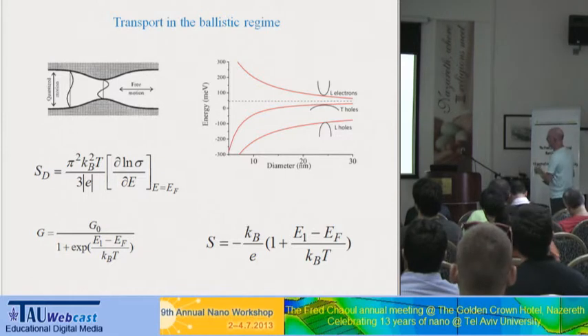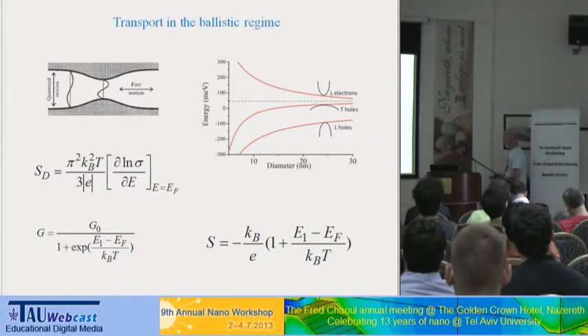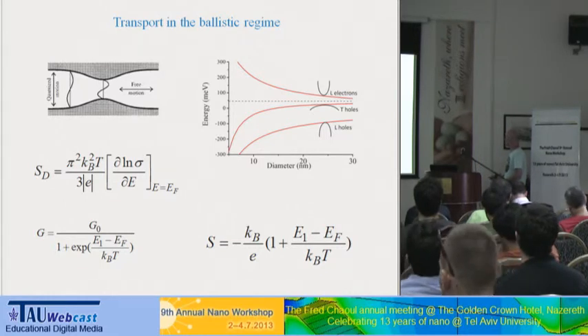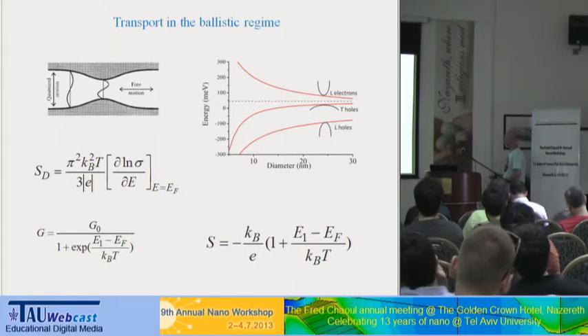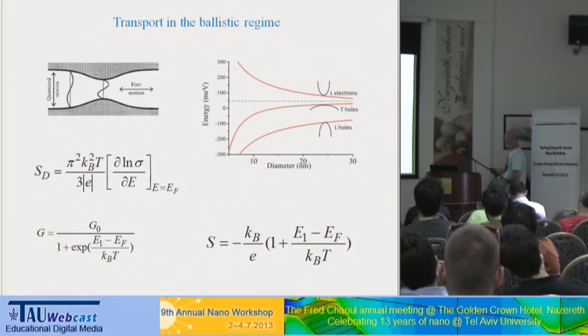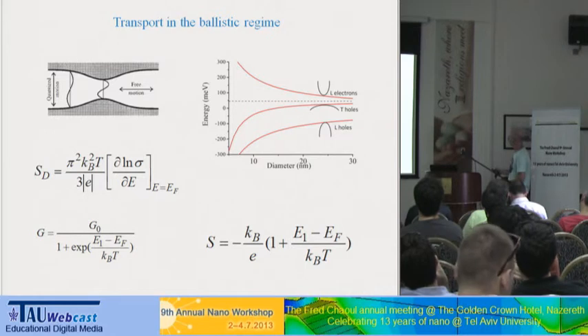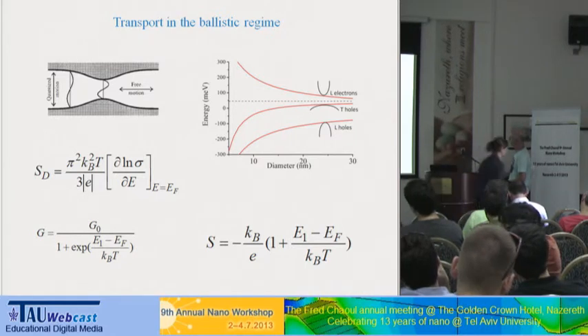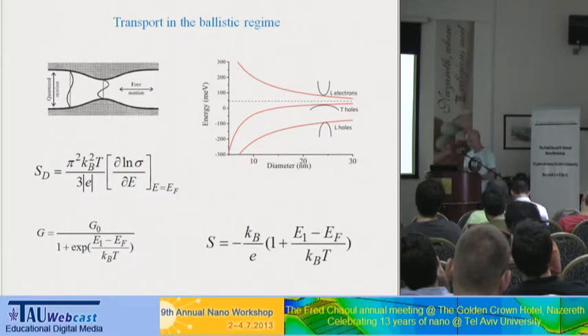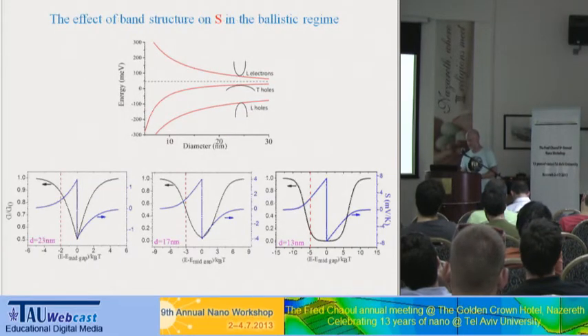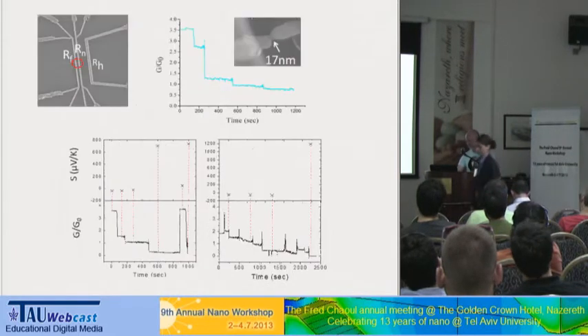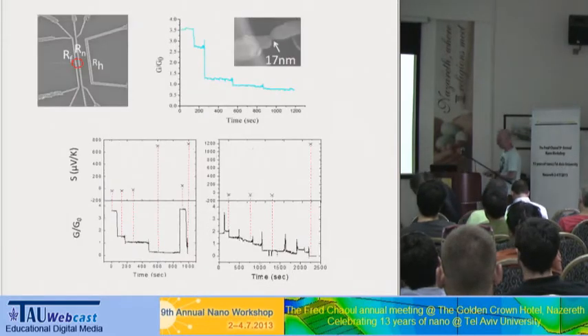You can actually get some very simple equation which should describe the Seebeck coefficient as a function of the position of the band edge relative to the Fermi level. So as you make this larger, S is going to be larger, and the distance here is between the dashed line here and the band edge of one of the bands that is contributing more to the conduction. I will skip this. This is telling what I just said more quantitatively, so I'll go straight to the results.